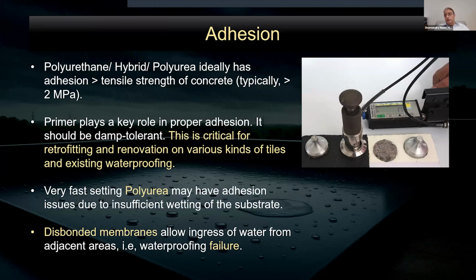Like we see in the picture on the right, we have done a dolly test, and the dolly has come off, and all the concrete below that has broken, and the coating has remained firmly adhered to the dolly. Right? So there are 2-3 factors which are responsible for this. One is primer. The primer plays a key role in proper adhesion.